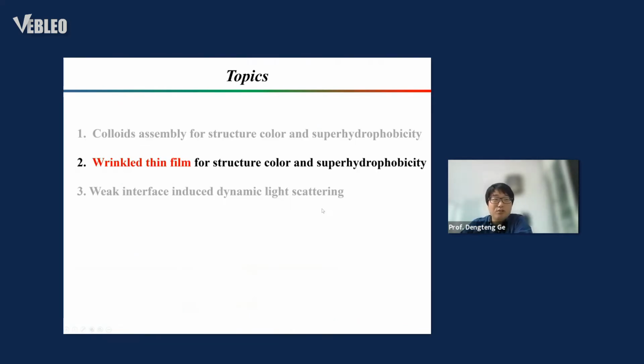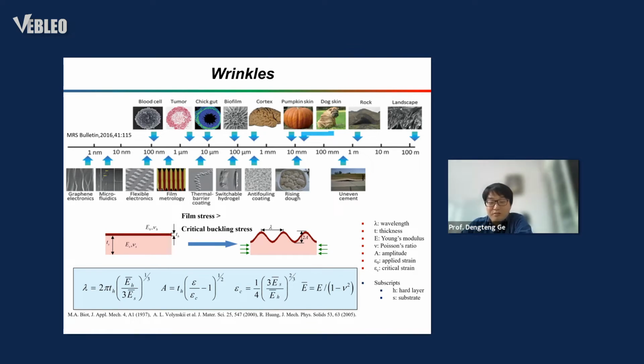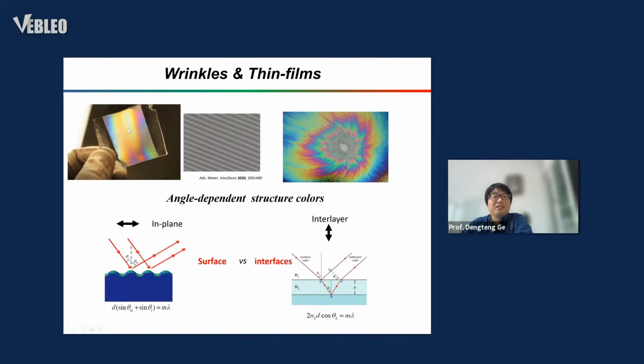The second part, we use the wrinkle to make a structure color and superhydrophobicity. Wrinkle is a very common mechanical phenomenon in nature. This phenomenon needs two layers, one rigid layer and one soft layer. Because of their modulus difference under deformation, the surface will become unstable and generate wrinkles. If the wrinkle is ordered, they also can generate structure colors. However, this one is similar to a grating. The color is angle dependent, and the thin film color is similar. So can we combine them together to make uniform colors?